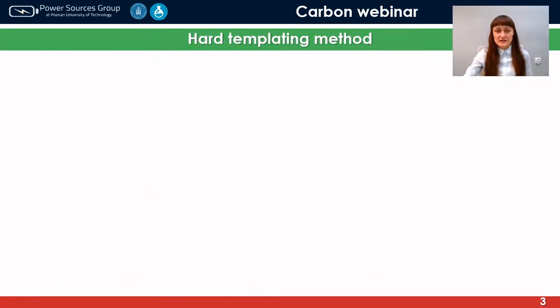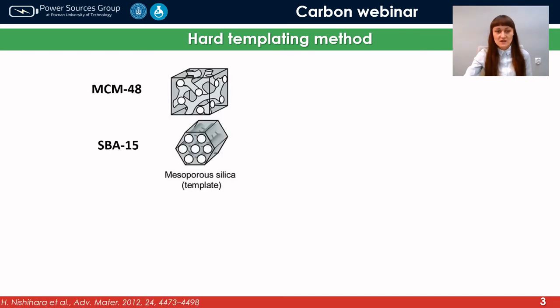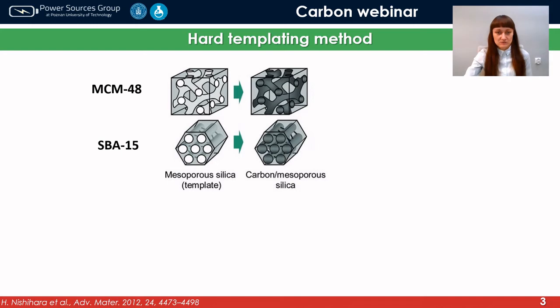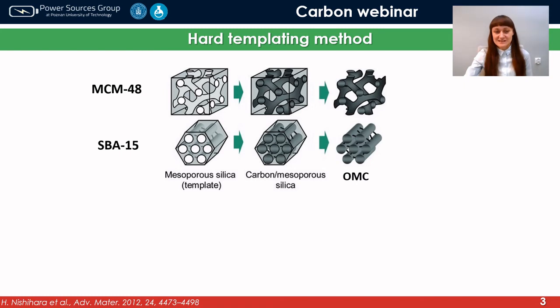A common method of obtaining such materials is the hard templating method, in which silica templates like MCM-48 or SBA-15 are used. In the first step, these silica templates are impregnated by an aqueous solution of sucrose mixed with sulfuric acid. Here the sulfuric acid plays the role of a catalyst. And then such a mixture is heated to the desired temperature in the range of 800 to 1100 degrees Celsius. After that, the silica template is removed, usually by a solution of sodium hydroxide mixed with ethanol, and in this case we are able to obtain ordered mesoporous carbons.